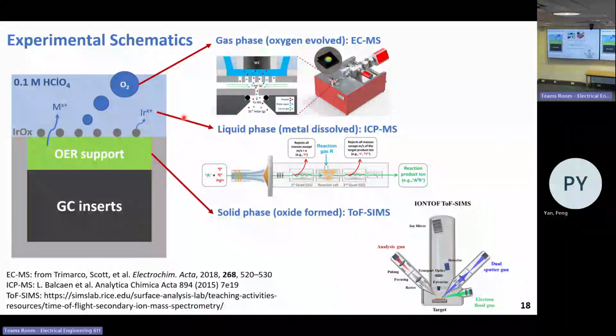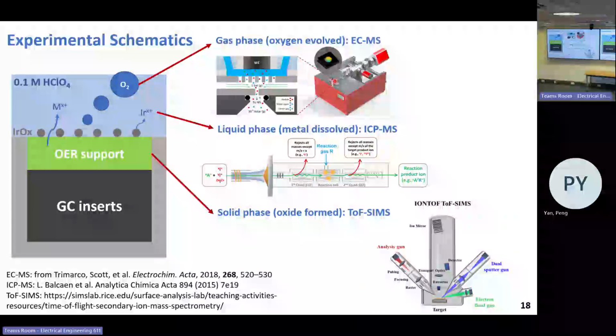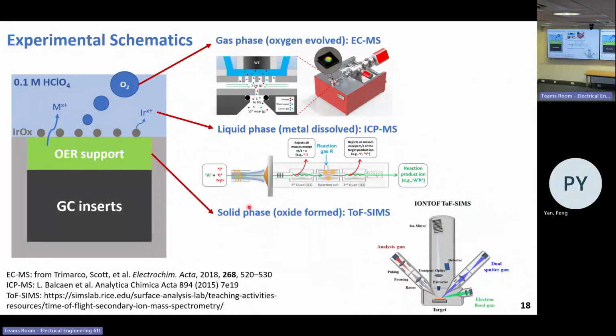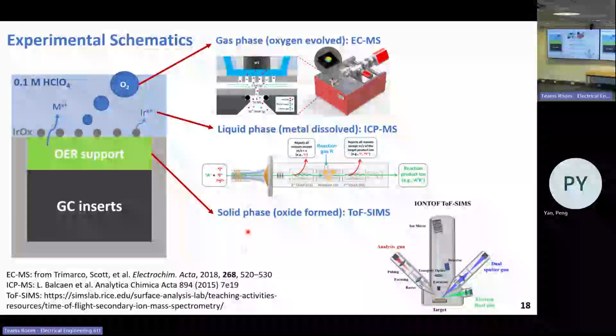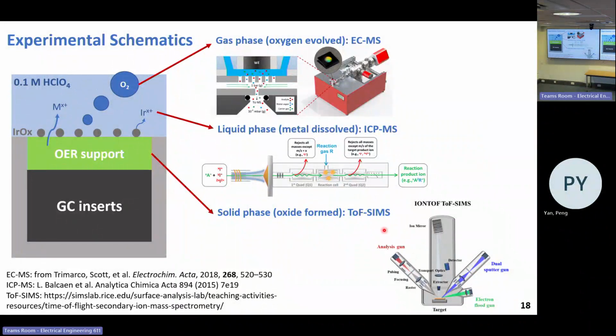Just doing it. In my project, I've used three types of mass spectrometers to look at gas phase, liquid phase, and solid phase of this reaction. First is electrochemistry mass spectrometry, where we can look at how much oxygen is being evolved during the reaction. For the liquid phase, like metal dissolution, we use inductively coupled plasma mass spectrometry to quantify how much metal dissolved. And time of flight secondary ion mass spectrometry is used to look at the solid phase, for example the thickness of the oxide layer formed on the support.